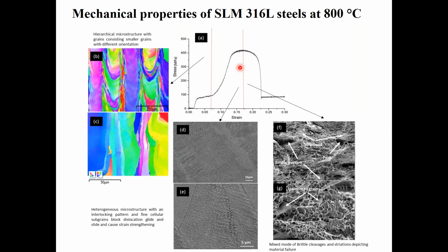And then we did the mechanical test at 800 degrees centigrade, which is quite a high temperature for steels, and we observe stress relieving, grain recrystallization, and grain growth in conventional steels. Whereas in this case, there's a lot of strain hardening happening, and we are getting a very high mechanical strength of 400 megapascal. The microstructure shows that the hierarchical structure is not changed or modified even at 800 degrees centigrade. So this heterogeneous microstructure is contributing even at 800 degrees centigrade towards the mechanical stability of the steel.